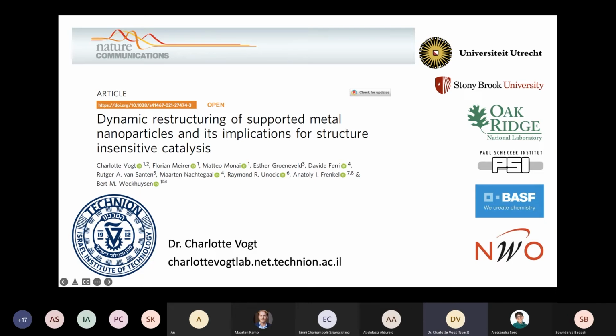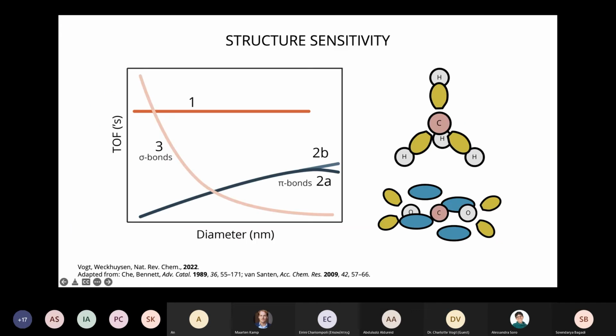So I want to talk today about a very fundamental concept of catalysis, something that's been empirically observed for decades, but really didn't have a good rational explanation, in my head at least, for a while. So to begin, structure sensitivity is, like I said, an empirically observed phenomenon. We have about 3 classes of structure sensitivity that we observe, or insensitivity. The first and most well-known maybe is an example is the Fischer-Tropsch reaction, where the bond cleavage of CO, pi bonds, is the rate determining step.